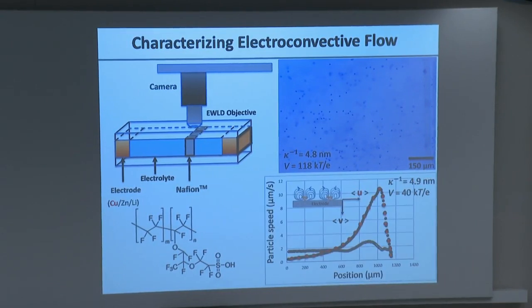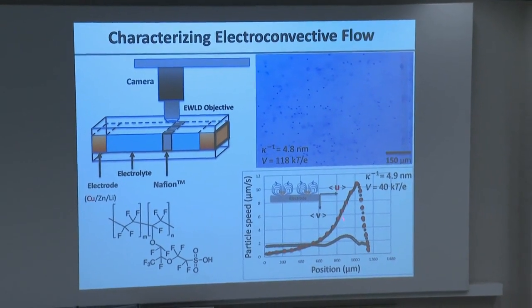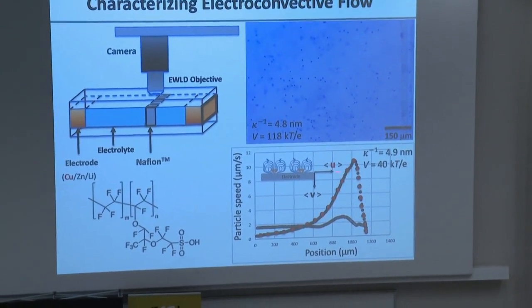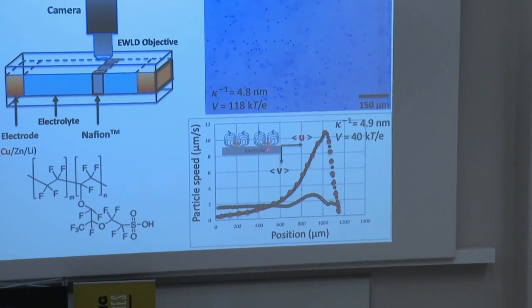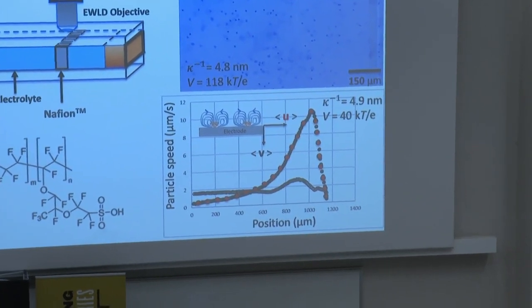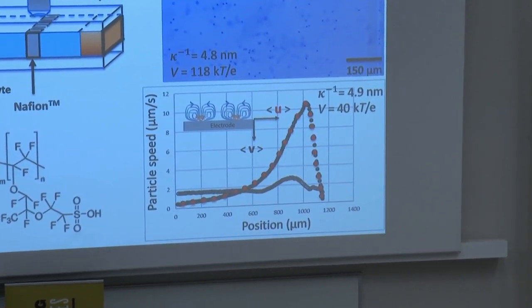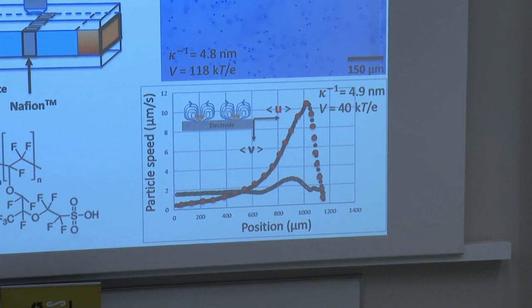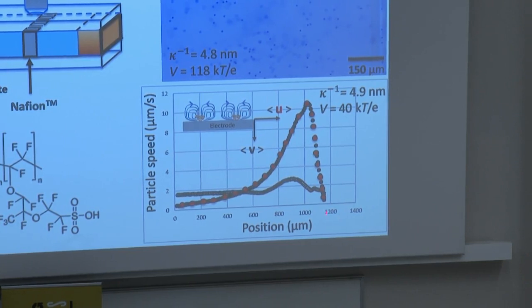We can actually map out the velocity profile in the fluid near the wall. And what we discovered is that if we now map out the velocity field based on the particles, the velocity has two dominant components. It has a component U that is parallel to the surface, and a component V that's actually perpendicular to the surface. So stuff comes in and goes out, kind of like that, okay? And so this is U, this is V. No, sorry, I lied. V, U, okay? Now what is even more interesting is that if you now monitor U as a function of distance from the wall, so the wall is here, right?